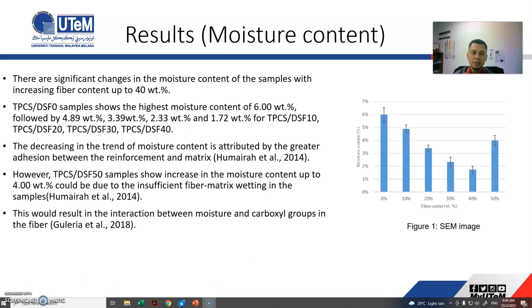As you can see here, the addition of fiber has significantly reduced the moisture content of the materials. The decreasing trend can be attributed to greater adhesion between the fibers and the matrix. However, for the 50% sample, there is a slight increment in the moisture content. This could be due to insufficient fiber matrix wetting in the samples, which results in interaction between moisture and the carboxyl group in the fiber. The fact that it can reduce the moisture content means that it can improve the stability of the materials, especially when in contact with moisture.